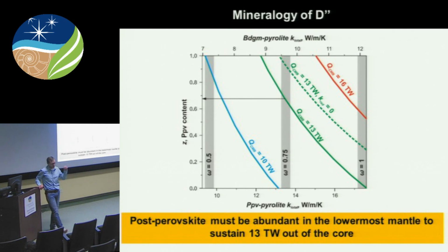So the total thermal conductivity of the rock that's bridgemanite rich should be very different from that of postperovskite pyrolite. Therefore, you can model what the thermal conductivity of these two hypothetical end members is, and what the postperovskite fraction should be in order to have the heat flow of 13 terawatts. And what these gray bars show you is the downward correction in lattice conductivity. I have said that I'm combining my radiative conductivity model with a lattice thermal conductivity model. But the lattice thermal conductivity model that I have is based on